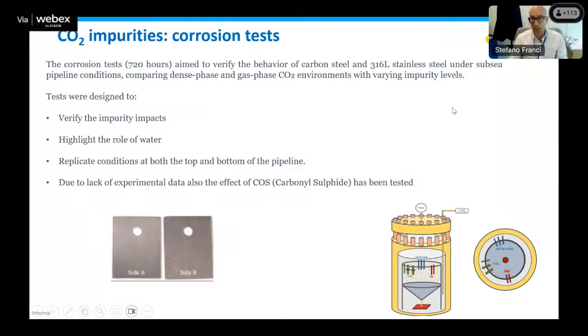The materials were carbon steel, standard piping and pipeline carbon steel, carbon manganese material, API and ASTM materials. And we added also some 316 with a crevice feature because we wanted to simulate any issue for the valve trims, which are supposed to be in 316. And so we wanted to test also some CRA, namely 316.